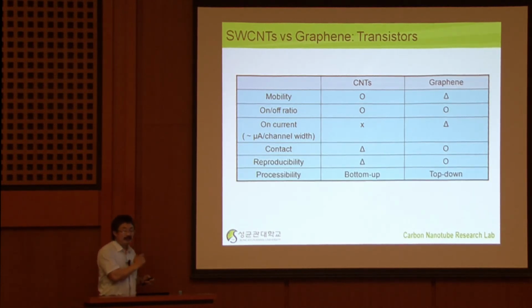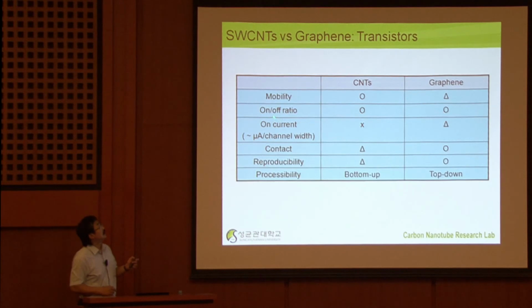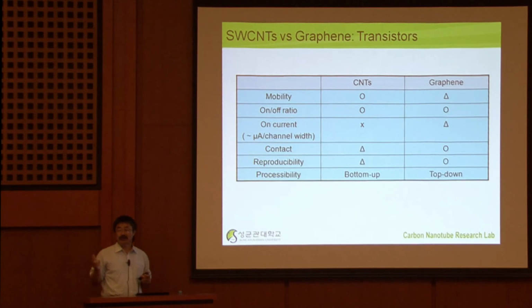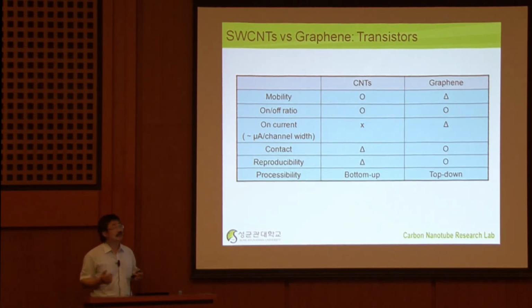If you compare all the device properties, like the mobility, carbon nanotubes are okay, but when we make a nanoribbon, mobility drops significantly because of this edge scattering. Unless you solve this problem, we are not guaranteed to have high mobility. On-and-off ratio, yes, if you can make a nanoribbon, you can have a high on-and-off ratio like 10 to the 6th or 10 to the 5th, similar to a silicon device.